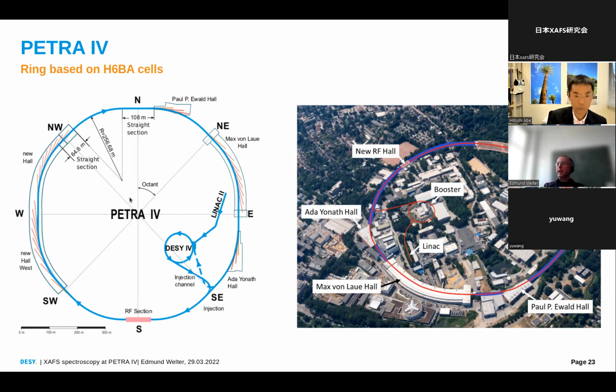So the plans for PETRA changed. The plans for the electron optics, for the lattice, changed about 1.5 years ago, and the planning started more or less again. We are now at hybrid 6-bend achromat cells, on a ring based on these cells, which have a lot of advantages compared to the design that was discussed before. The other design was a typical DESY design with a highly asymmetric ring. Now we have a more or less symmetric ring, and the main advantage is that many beamlines can remain more or less at the same space where they are today, especially in the Max von Laue hall.